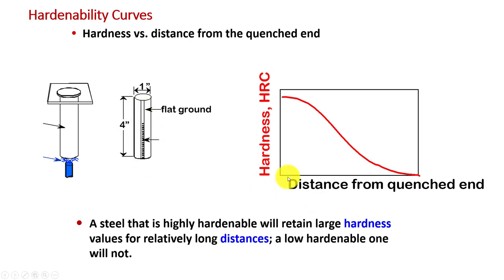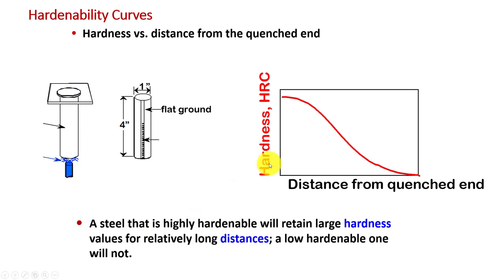The distance from the quench end — this is going to be the quench end right here — and this is the hardness. We're going to see these values being harder and getting softer over distance. That reflects time of cooling because it's going to take a long time for it to cool upward along the bar. We're going to see that time, distance, and hardenability. Different steels with different carbons and alloys are going to have different plots in terms of hardenability.